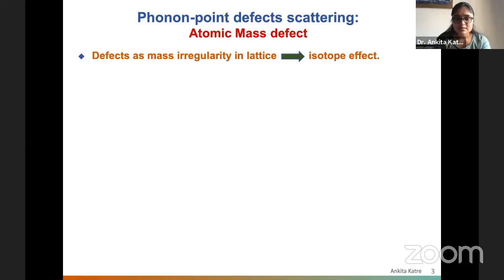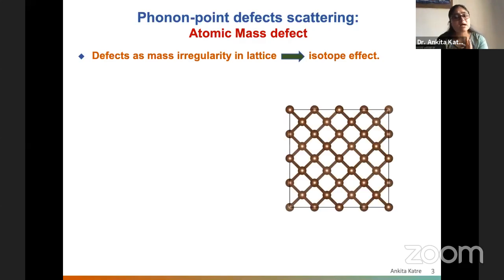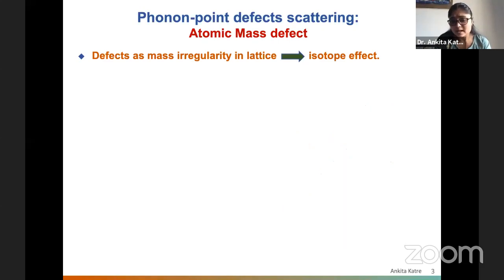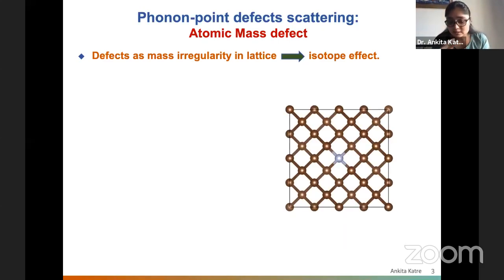So that means we are just treating these defects as some mass irregularity in the lattice. That means it's just the isotope effect that we are seeing here. If we just take this cartoon here, and if we see that in the whole lattice, we just have one atom which has a different mass, however, the bond lengths are not changing. All these bonds which it is connecting to its neighbors are not changing at all, and nothing else is changing. It's just the mass that is changing for this defect.